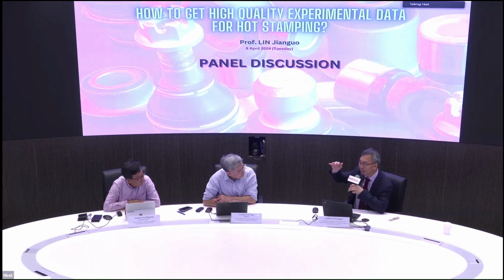Okay. The main thing is, for steel, for example, the initial structure, which I did not mention here, is generally speaking 30% bainite and 70% ferrite in the initial stage. When we increase the temperature to about 925 degrees C and keep it for 1 to 3 minutes, it can be austenitized. At that time the crystal structure changes and the material becomes austenite. The ductility becomes very high, and all dislocation densities, apart from the natural defects, disappear.